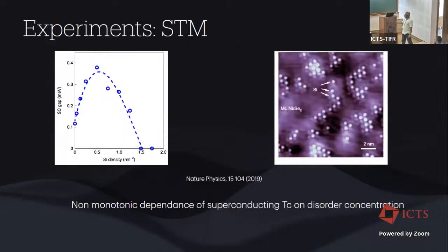Lastly, if you look at the superconducting TC as a function of, for example, a non-magnetic impurity like silicon sitting on the sample, as a function of silicon concentration, the superconducting gaps in local measurement seem to go up and then to go down. Now, this in itself is interesting. You can say that this probably comes in from the fact that maybe the CDW is getting suppressed, so there is lesser competition between CDW and superconductivity. But then again, if the CDW is getting suppressed and you have a conventional S-wave order, you do not expect this type of behavior to show as a function of non-magnetic impurity concentration. So this is also evidence that there is more to the story.